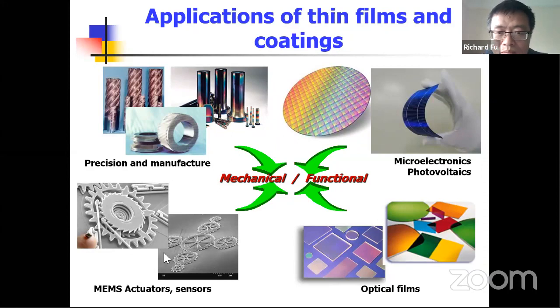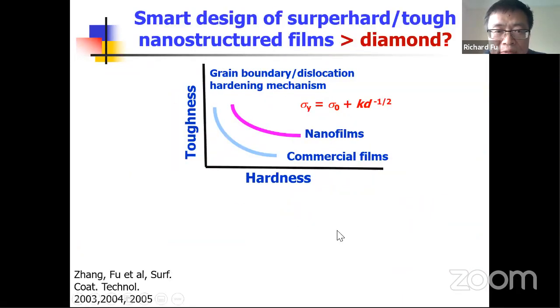So basically, for the mechanical property, there is a very strong requirement for the coating or thin film to have both very high hardness and also very good toughness. For hardness and toughness, it's quite difficult for a coating to achieve both properties. If we increase the hardness, normally the coating will become quite brittle and cracks easily form and propagate. So there is a very good design using the nanostructured thin film, which can achieve both high toughness and hardness. This is based on the Hall-Petch effect. If we reduce the crystal size of the coating, then we can achieve very good hardness, and also the crack propagation will be reduced.